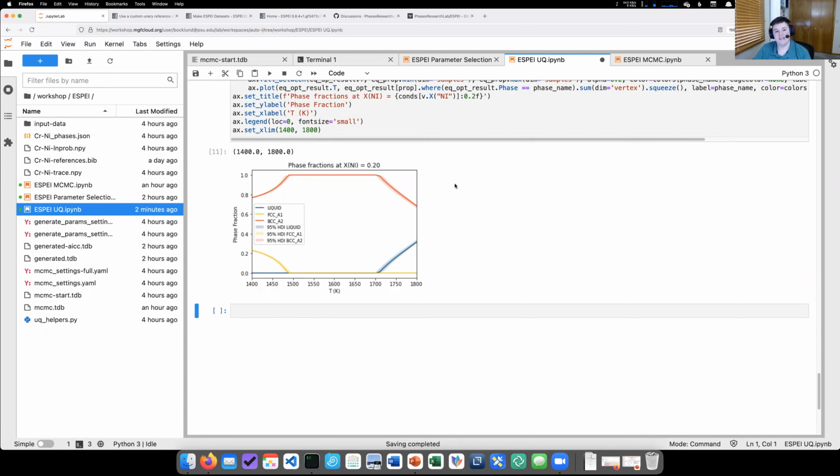That weight concentrated the posterior probabilities much more than in that copper magnesium analysis. All of the phase boundary data is heavily weighted, and so anything that has to do with equilibrium, phase stability, or regions of energy parameter space close to stability is going to have a lot lower relative uncertainty. That's what we see here as compared to the other examples.